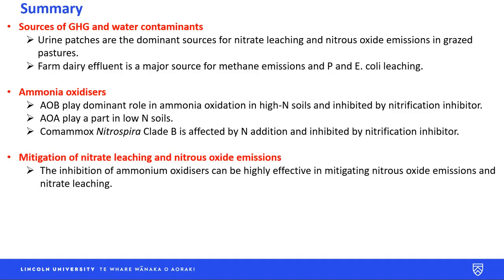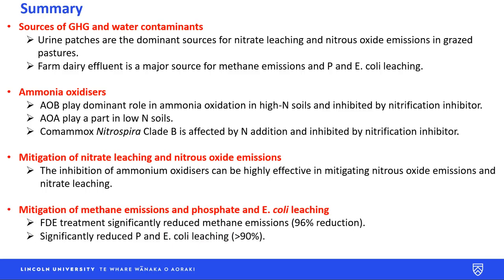So by inhibiting these microbial communities, the ammonia oxidizers, we can significantly reduce nitrous oxide emissions and nitrate leaching. And by treating your farm dairy effluent, you get all three benefits: methane reductions, phosphate leaching, and E. coli leaching. So essentially, we have taken care of a large part of the environmental problem from the grazed pasture systems: nitrate leaching, nitrous oxide emissions, phosphate leaching, E. coli leaching, and methane emissions from the effluent pond.